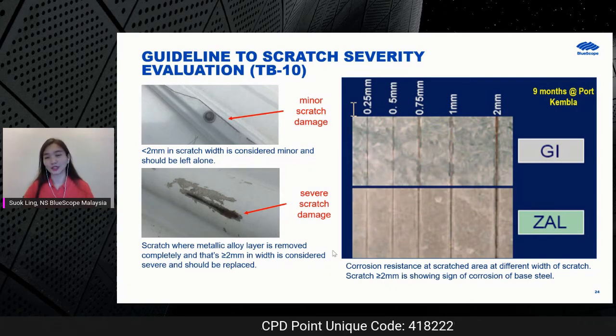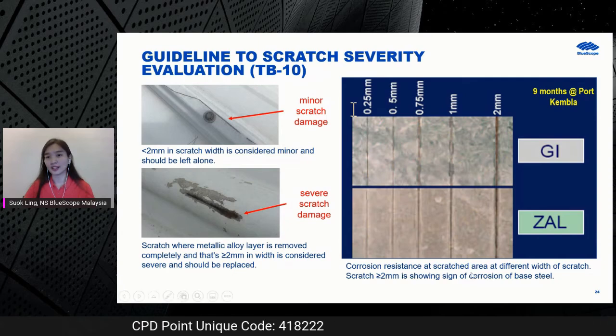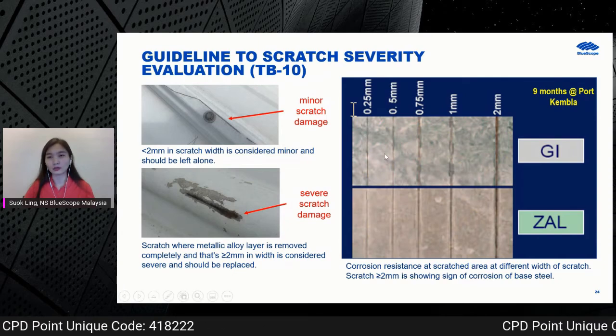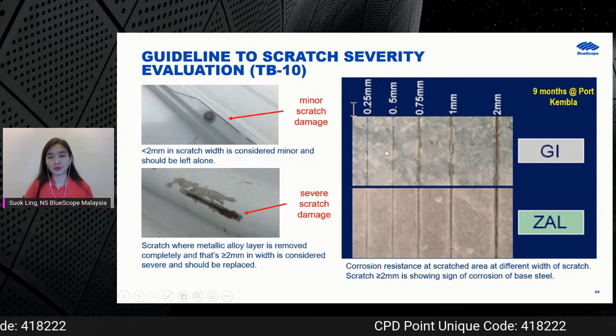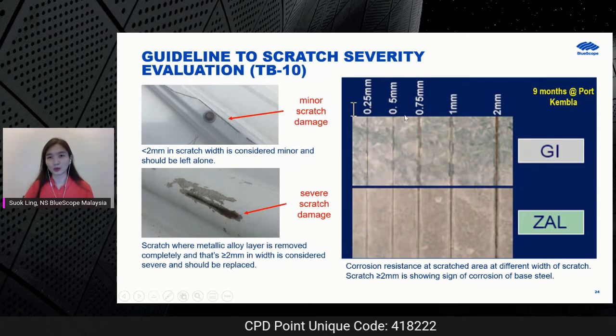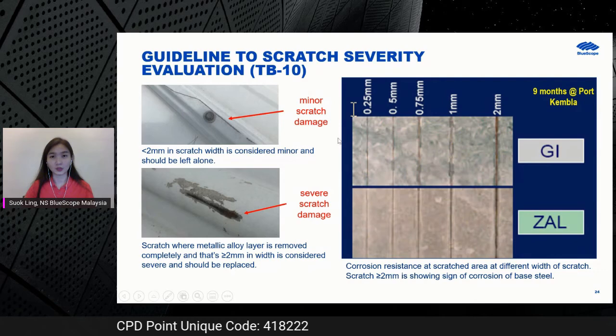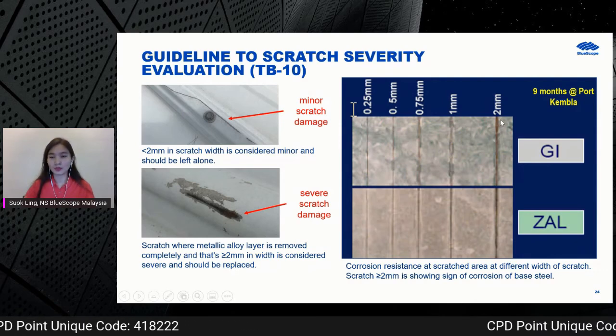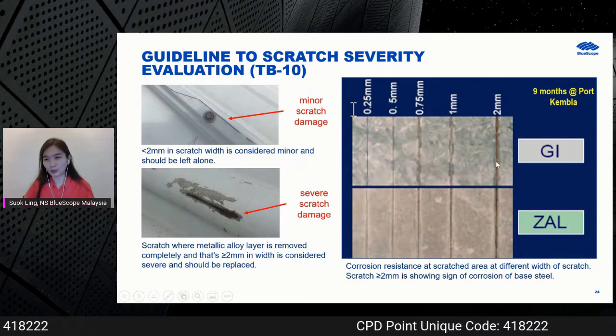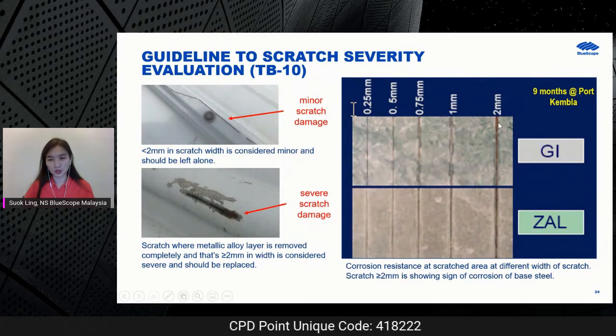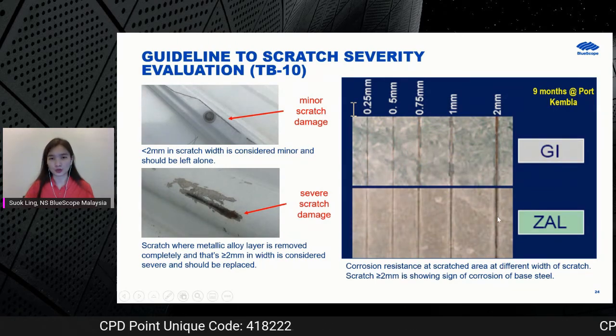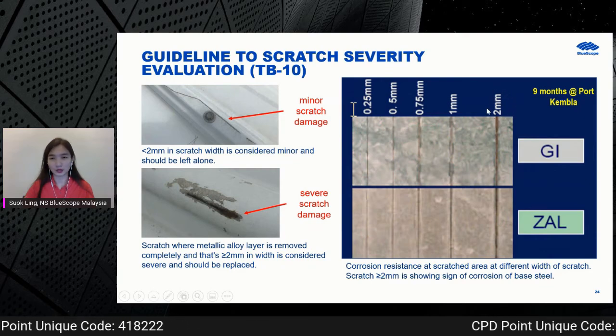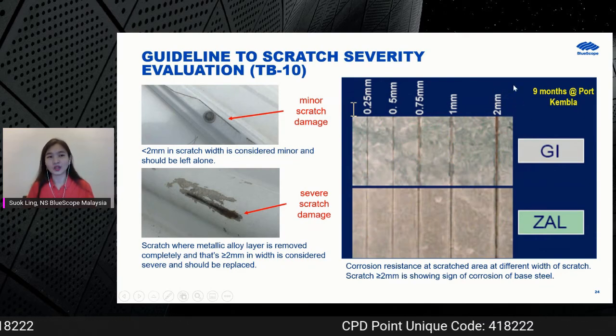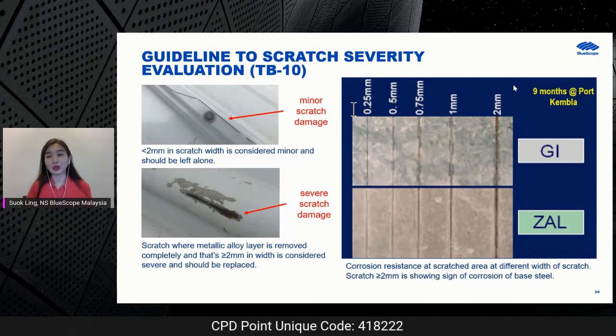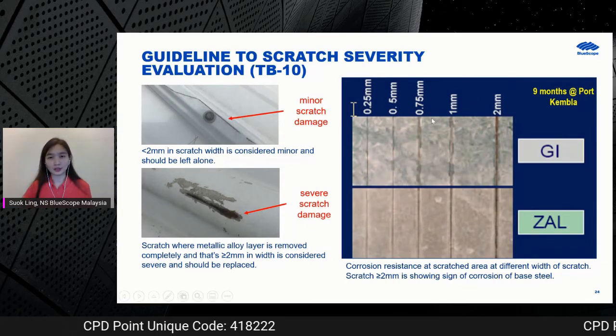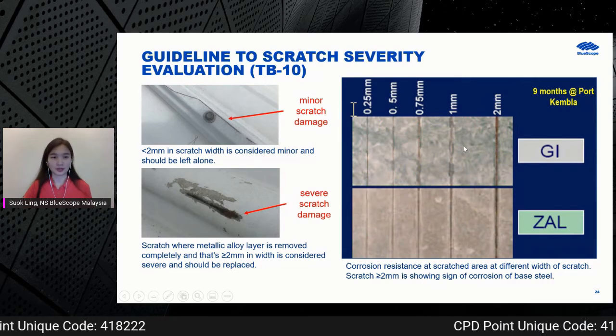And why are we benchmarking 2 mm as our guideline? Because we have conducted a lot of studies on the scratch width. For example, what you can see over here is 0.25, 0.5, 0.75, and even 1 mm. And then we conducted up to 2 mm. From our study, from 2 mm onwards, it starts showing red rusting corrosion. So we benchmark any scratch width that shouldn't exceed 2 mm, and those we classify as minor scratches.